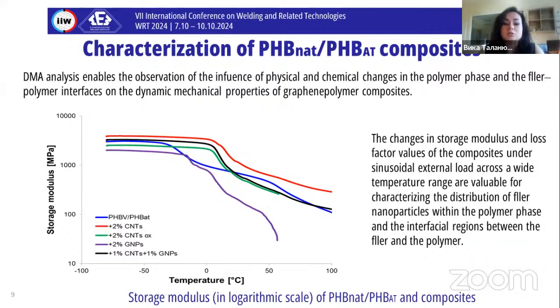And the next step is characterization by DMA, because we need to see how the structure changes with our different fillers. In these pictures, you can see how the glass transition temperature changes in the DMA analysis, because a normal blend of PHB and amorphous PHB has a higher temperature, but when we put some kind of fillers in, it changes a little bit. You can see it in this part of the pictures, along with the storage modulus, loss modulus, and loss factor values.